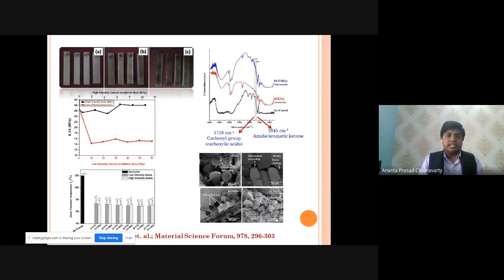At low intensity the strength decreased, and at high intensity the strength improved. From that I concluded that at high intensity doses the polymer may be cured to the desired extent, so that its strength improved. Similarly, their glass transition temperatures at high intensity doses are greater than at low intensity doses, and the composite exhibits a color change with very good strength.